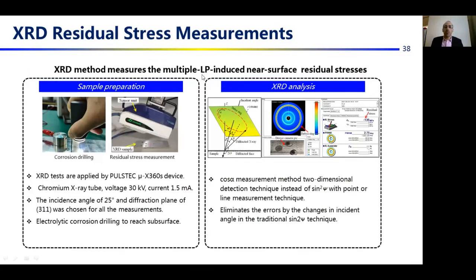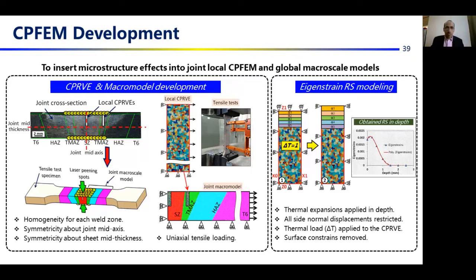The XRD method measures the multiple laser peening-induced near-surface residual stresses. XRD tests are applied by the Pulstec device, and electrolytic corrosion drilling is also used to reach the subsurface areas to measure the residual stresses in the subsurface. And the cosine measurement method in the two-dimensional detection technique is used for measuring the residual stresses because of its lower errors compared with the conventional sine method.